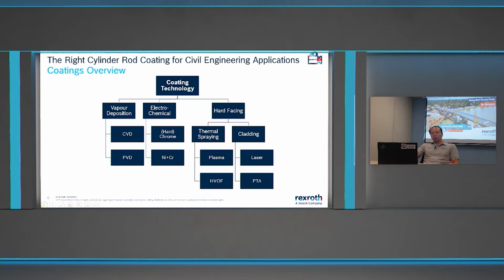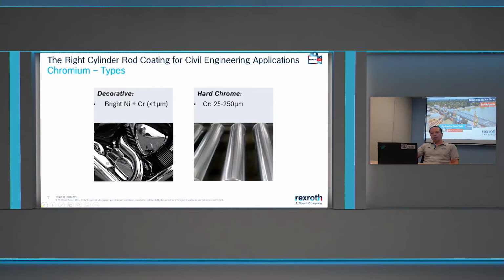Talking about the coating technology, we have different technologies. In my presentation, I will focus on the electrochemical and the hard facings. Talking about the electrochemical first, we have the hard chrome plating. So the hard chrome plating tends to be thicker than the decorative plating. The thickness of the hard chrome plating is from 25 microns to 250 microns, while the decorative chromium plating has a thickness of 1 micron only.